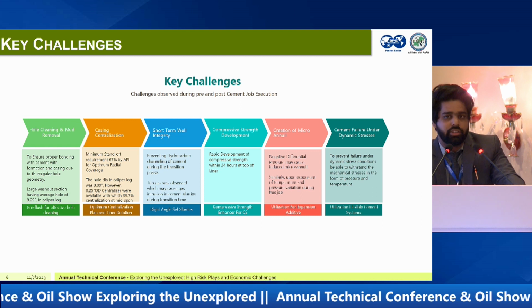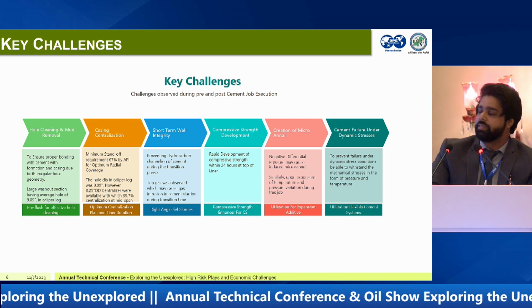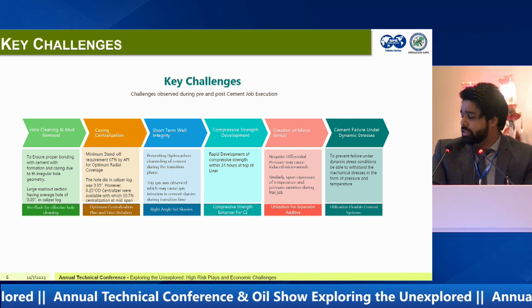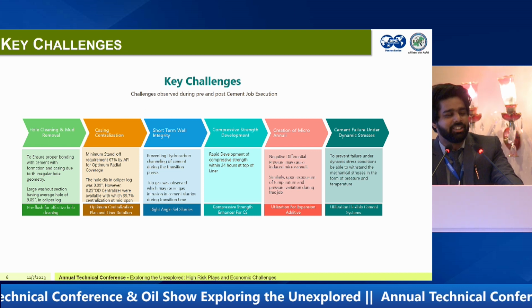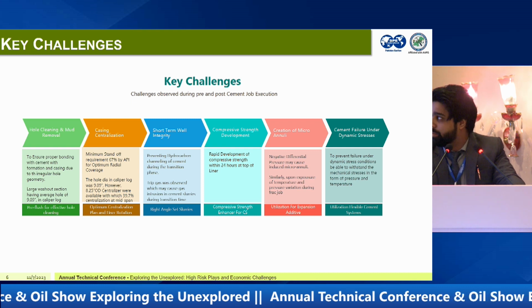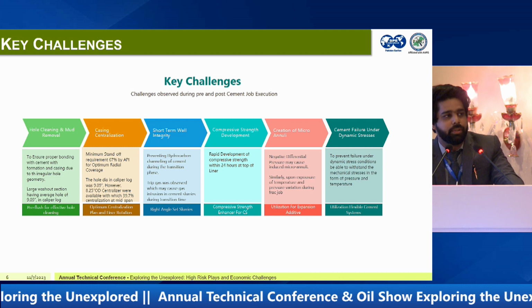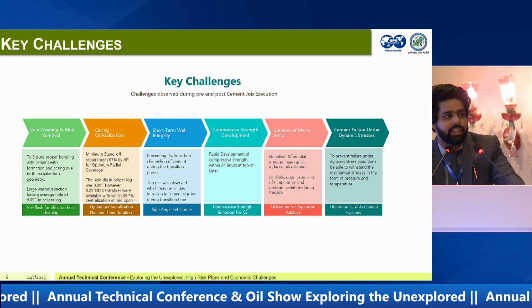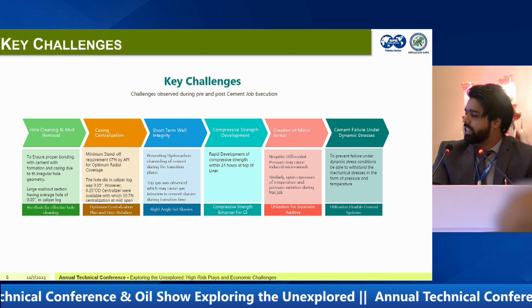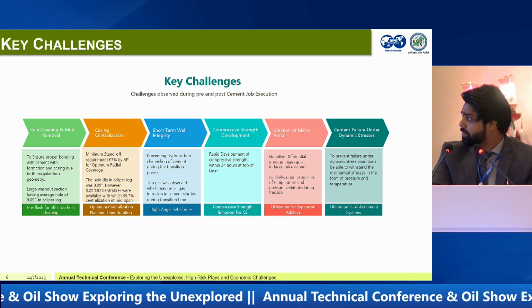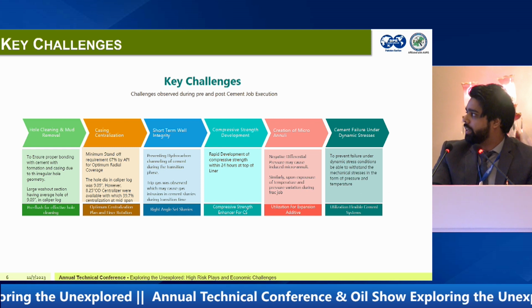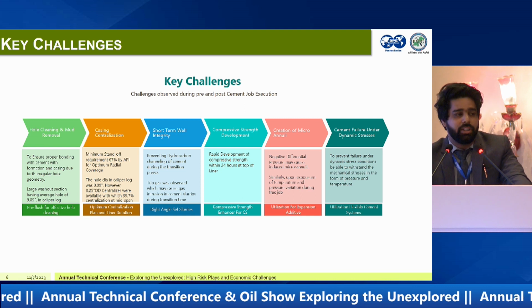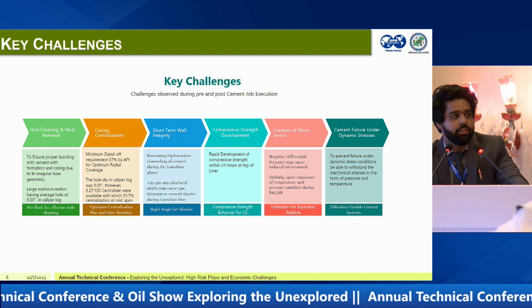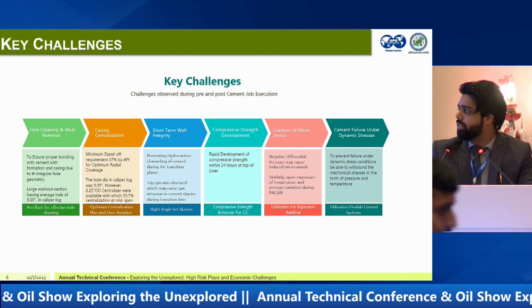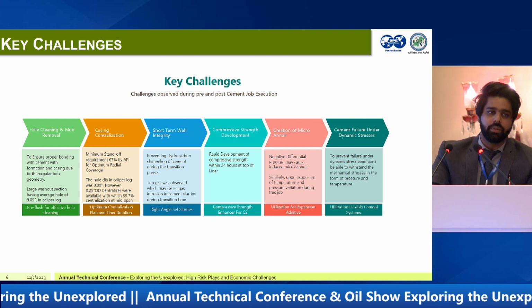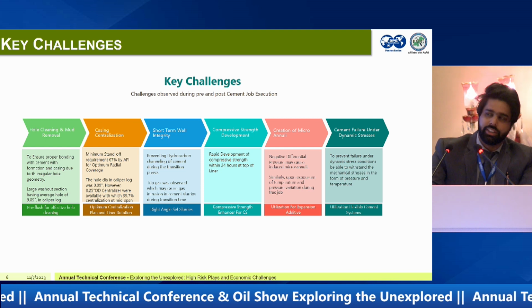Then there was another challenge, the creation of microannulus, which we usually observe due to negative differential pressure, and induced microannuli can form. Similarly, depending upon the exposure and pressure and temperature variation, a microannulus can be created in the wellbore. To mitigate this challenge, we incorporated expansion additives so that our slurries can expand after being placed at a particular depth. After that, there was a key challenge: cement failure under dynamic stresses. Cement failure during dynamic stresses is quite common, and to overcome this challenge, we utilized flexible cement, and with its help we overcame the challenges that were considered.